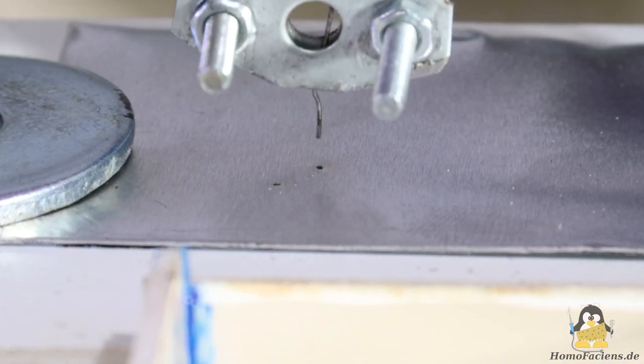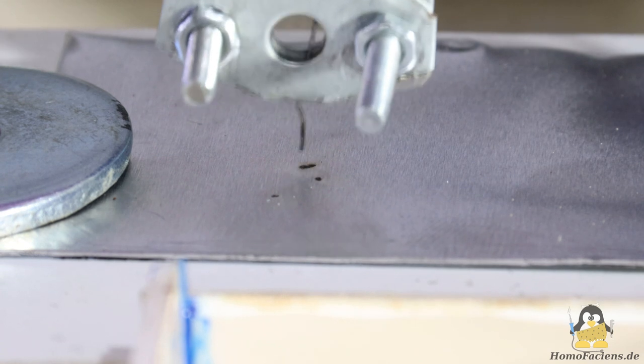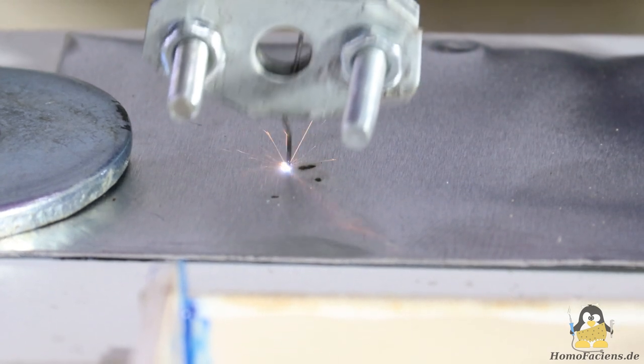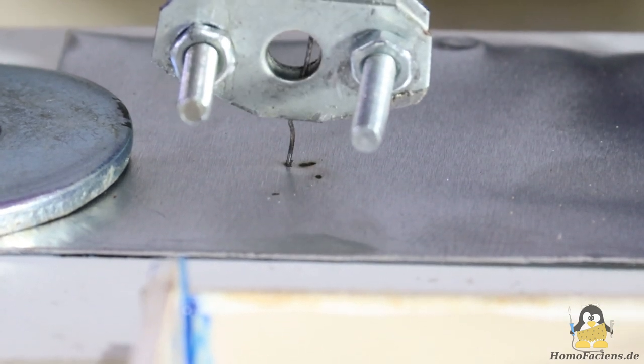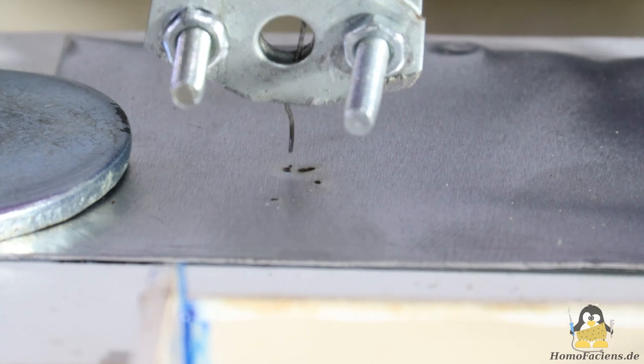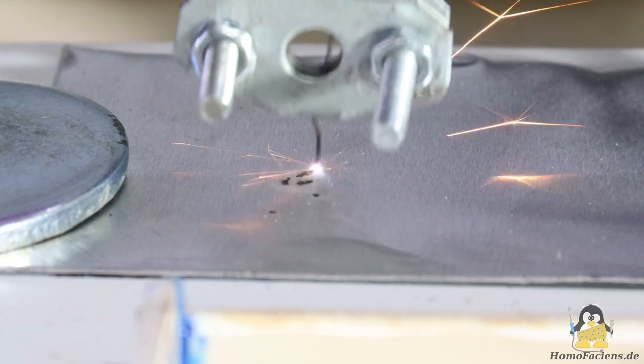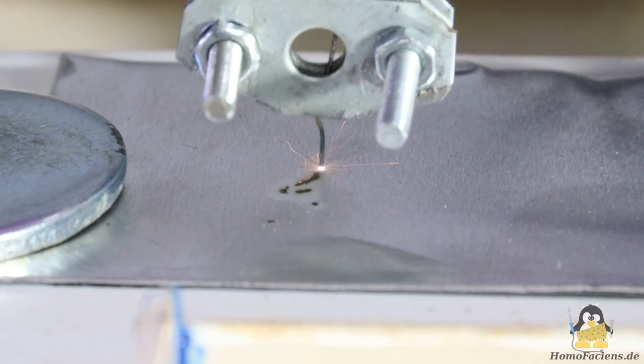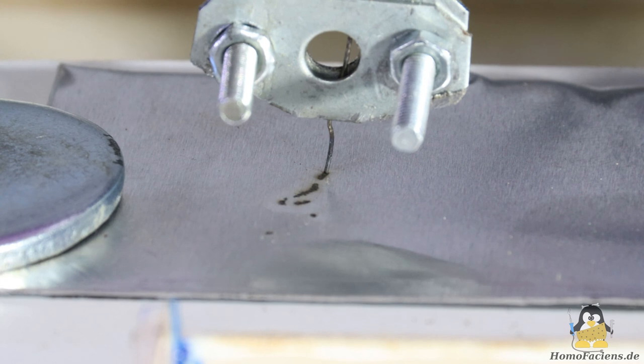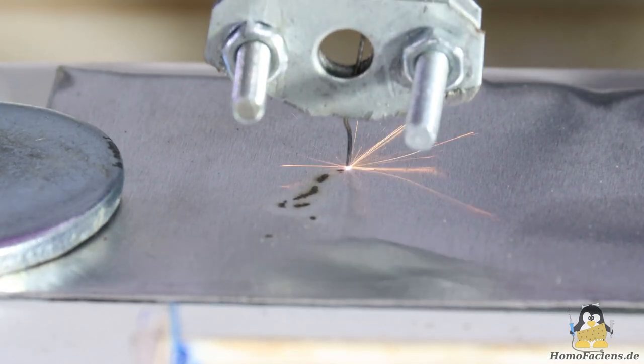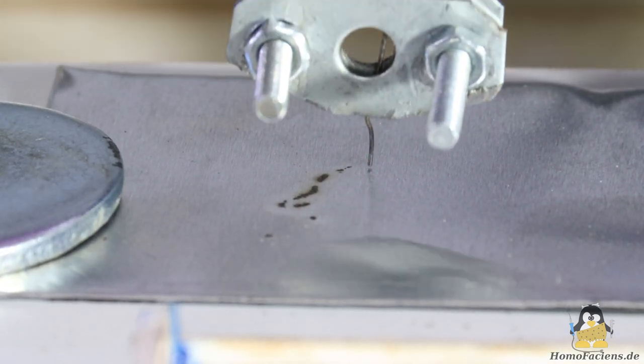Aluminum is engraved here. This doesn't work with the steel wire. Aluminum forms a thick, insulating oxide layer in the plasma of the spark, which means that contact with the workpiece is not restored when the Wagner hammer lowers.